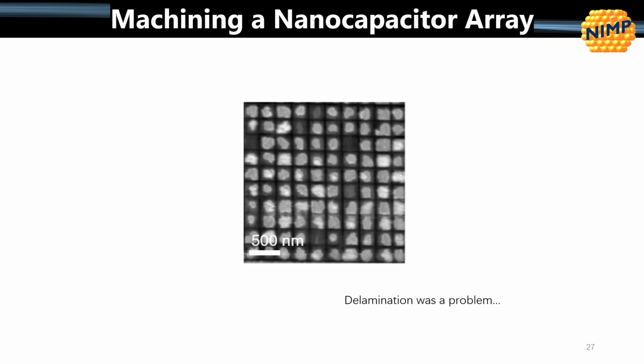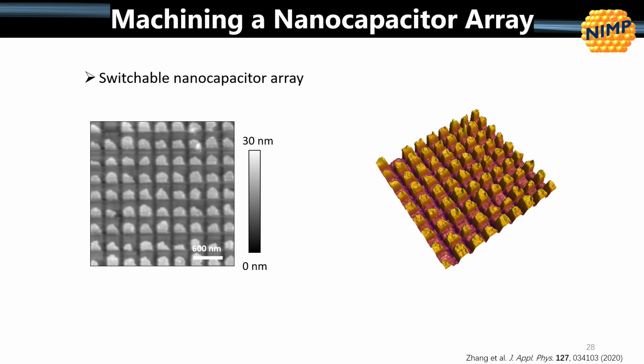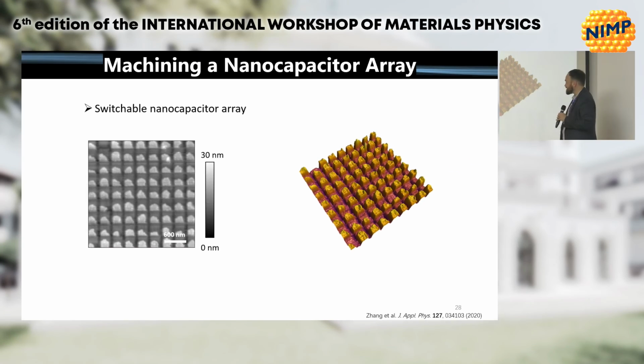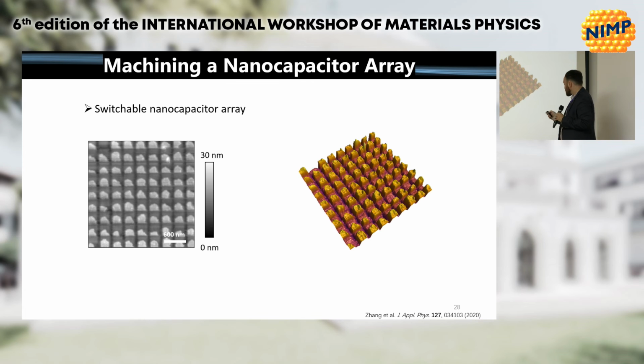We wanted to see if we could carve metallic electrodes. So again, this isn't carving all the way through the material, it's just carving the metal on the surface and maybe a little bit deeper. But delamination was a problem. So trying to fine-tune and optimize that was a challenge. But this was the best that we got, so there's at least some metal left on all of these elements, and every element was switchable, as shown here.